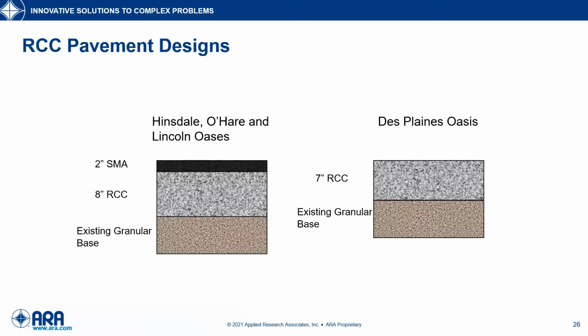So here are the pavement designs that were used. Like I said, 3 of the 4 sites had a 2-inch asphalt surface on 8 inches of RCC. The Des Plaines Oasis was unique because it was a shorter life pavement, so we didn't use the asphalt overlay and the pavement was a little thinner.